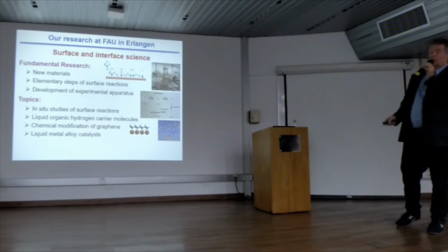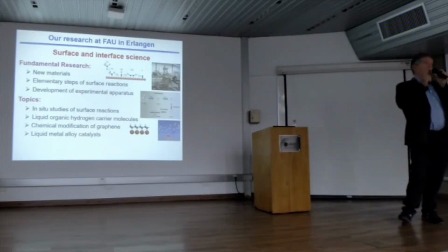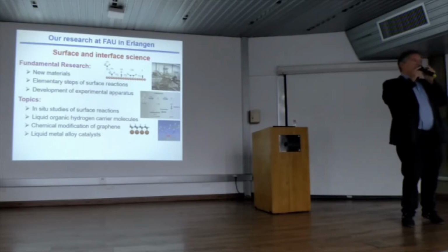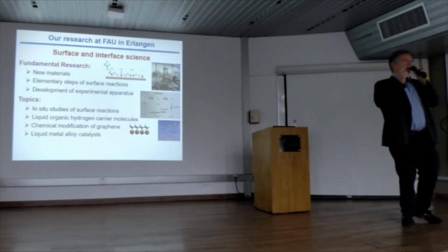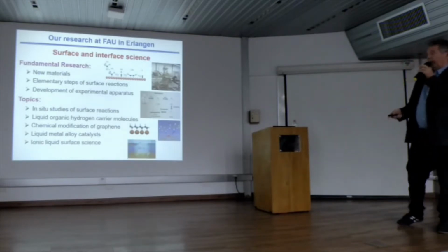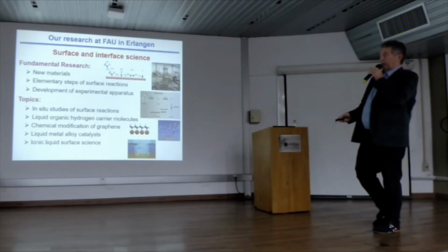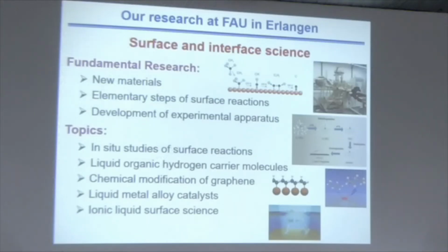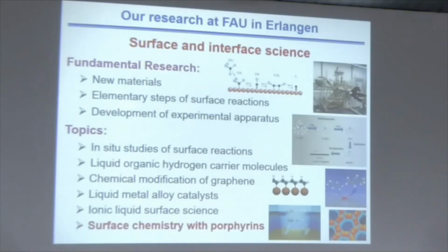And these catalysts don't coke. Because for coking, you need to break a carbon-carbon bond, and you need 2 adsorption sites for the product. If there's only one platinum atom, you don't break the bond. Then we work with ionic liquids. Ionic liquids are liquid salts made of molecules that are liquid at room temperature and have no vapor pressure. There's no system with no vapor pressure, but a very, very low vapor pressure. And finally, we work with porphyrins, and I'm interested in the surface chemistry of porphyrins. And this is the topic of today's talk.